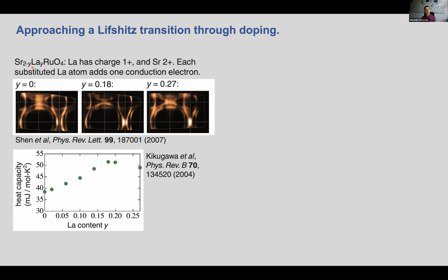So this is substitution with lanthanum. Lanthanum dopes electrons into the system, so that expands the electron-like Fermi surfaces. And we see that the gamma sheet here touches the zone boundary at a lanthanum content of about 0.27.